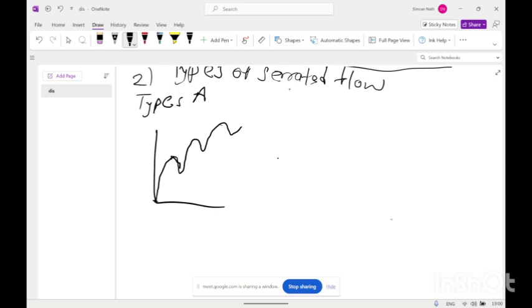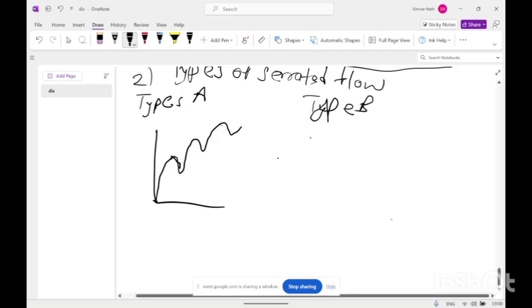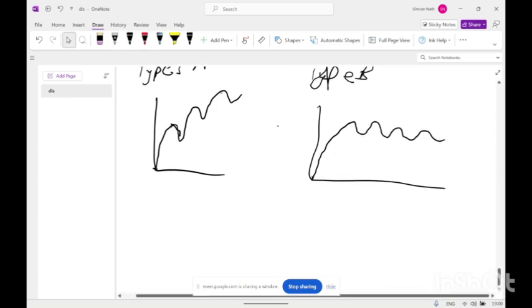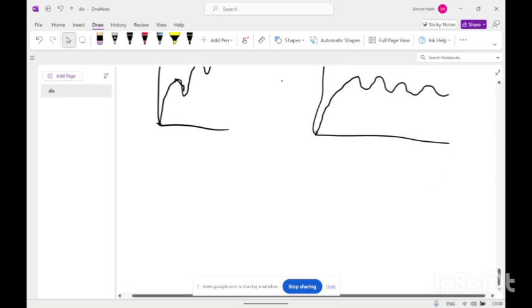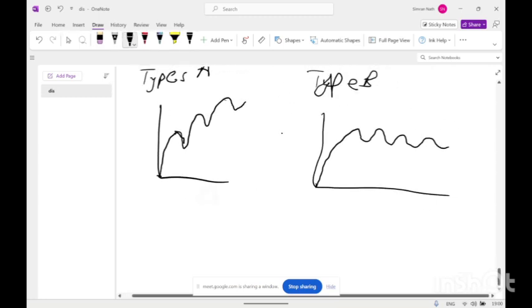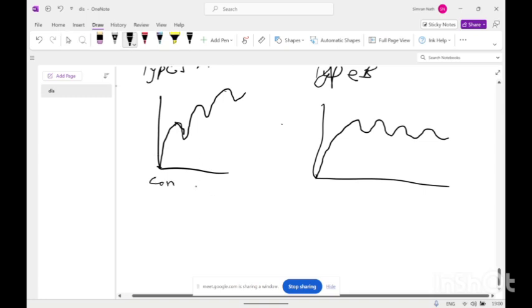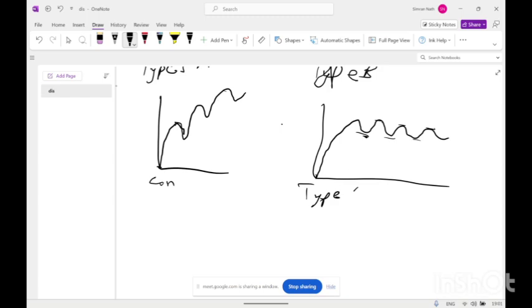Second is the type B, there is a smooth transition of the decrease and increase in stress level. For type A there is a continuous progress of the deformation band, while for type B the humps and valleys describe that the deformation band was stopped and the nucleation of a new deformation band occurs, means it is the disappearance of old bands and initiation of new bands.